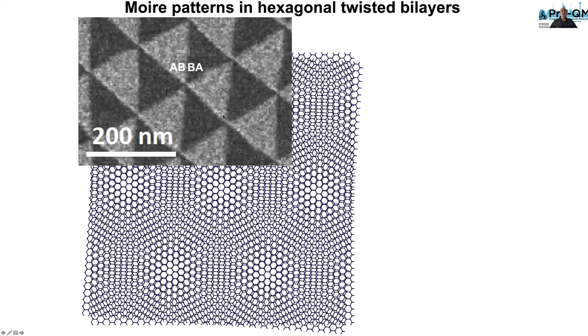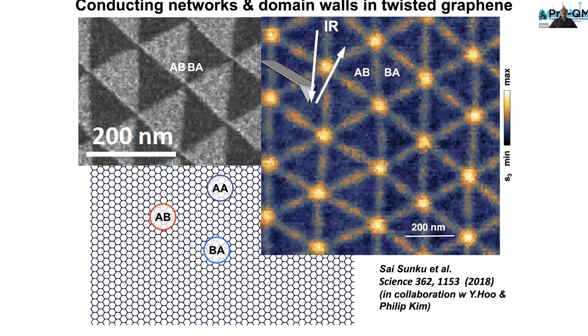The net result is that you have a triangular lattice that is seen directly in TEM images in two twisted layers of bilayer graphene. We see this triangular lattice very clearly in near-field infrared images. So here the wavelength of infrared light is chosen such that no polaritons are traveling yet. This is a readout of a local contrast due to local conductivity in this type of structures. You see that the contrast associated with the domains themselves is basically indistinguishable, but the contrast at the domain walls is enhanced, and that's consistent with enhanced conductivity associated with these domain walls separating triangular domains.